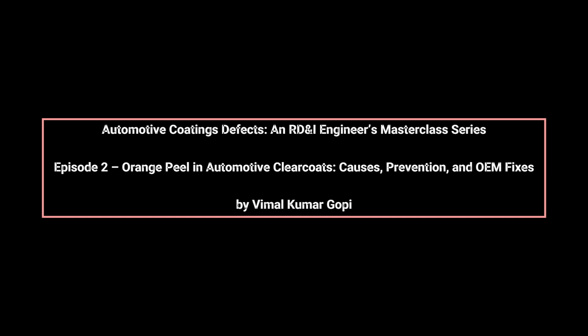The root causes of orange peel can be divided into formulation, process, and environmental factors. On the formulation side, viscosity plays a critical role. High low-shear viscosity prevents the wet film from leveling under surface tension before gelation occurs, while improper solvent blends accelerate skin formation. Fast solvents evaporate quickly from the surface, reducing open time, whereas insufficient medium and slow solvents hinder internal flow, locking the texture prematurely.